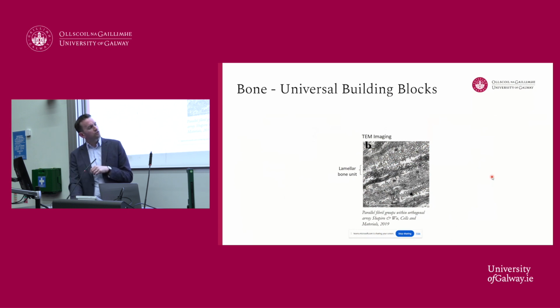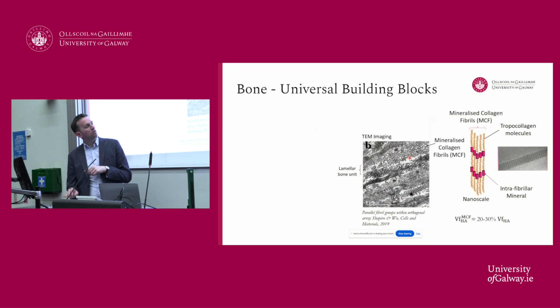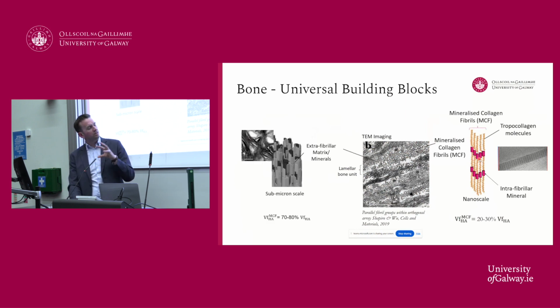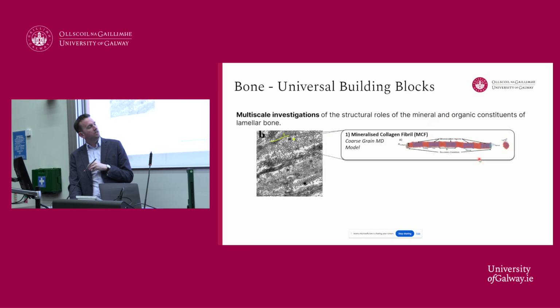So this is a microstructure image of bone tissue, and you see a similar structure to some of the composite materials that you see here. The small fiber-based structures are these mineralized collagen fibrils. So these are collagen molecules, again, with your mineral crystal that comes in here. And then the other piece is a mineralized matrix, okay? So we looked at developing a couple of models, and this was work that Madi Tabakal did. Madi was a postdoc that joined me from Iran, and he looked at developing coarse-grain molecular dynamics models for these materials, for understanding these collagen fibrils.